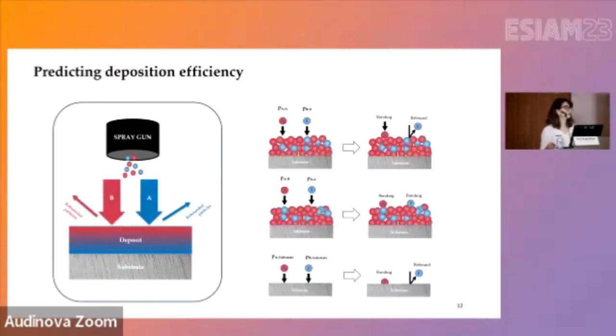And that's why when we are mixing two powders, let's say in a 50-50 volume fraction, what we get in the deposit can be very different from 50-50. So it's very important to be able to predict and estimate what we have in the deposit based on the blended powder.